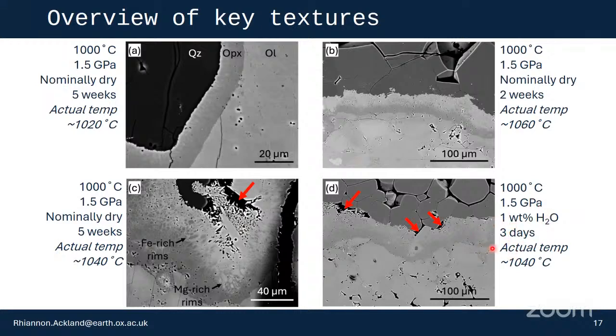And in experiments that I ran for a long period of time, 5 weeks, or in a water-present system, I saw void space opening up at the quartz interface. The void space is opening up due to the negative volume change of the reaction. And into this void space, we see large euhedral crystals of orthopyroxene growing.